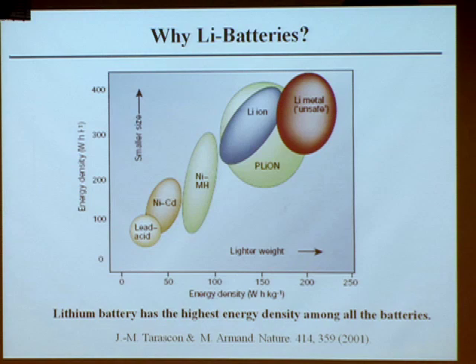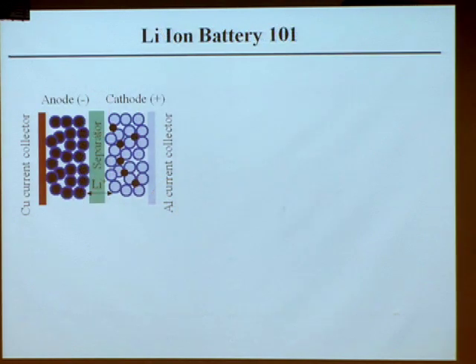Now let me show you the first example on the nanowire lithium-ion batteries areas. We care about lithium-ion batteries, among all the battery technology, because it produced the highest performance so far in terms of the energy density per unit volume or per unit weight, much better than nickel metal hydride, nickel cadmium, and lead acid batteries.